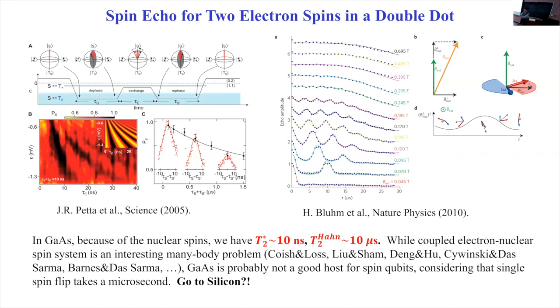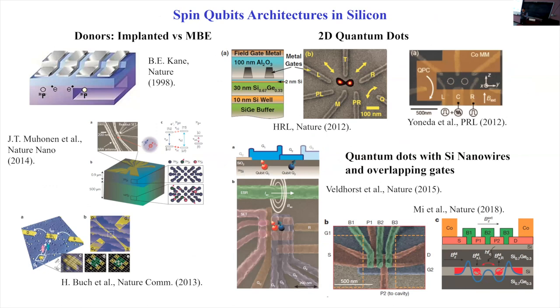So you're going to the low tide where the waters are gone, or only little puddles are left. You're not screening anything anymore. And so the electrical disorder is all revealed, right, from the dopants and everything. And so the high mobility in the quantum Hall samples of gallium arsenide really has no implication for a quantum dot with qubits. And so with silicon, which traditionally always has relatively low mobility in those high density regimes, at the low density regime, if you try to remove all those charge disorder and charge defects, then silicon is no worse. So that also allows people to move more comfortably into silicon from gallium arsenide.